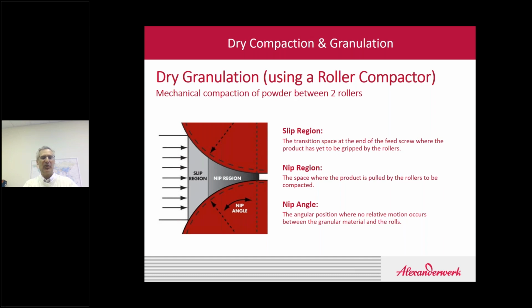So in the slip region, the particles are rearranging themselves, basically finding a space that they can fit into. And then in the nip region, the particles have no more mobility. They're simply being compressed. They get compressed to the point where the two counter-rotating rolls are at their smallest point, and that's going to also determine the thickness of the flake coming out of the machine.